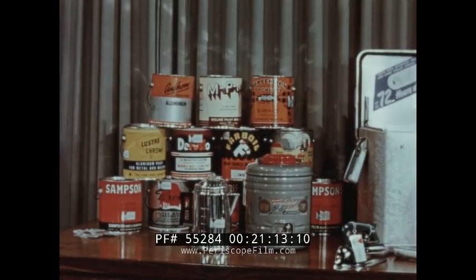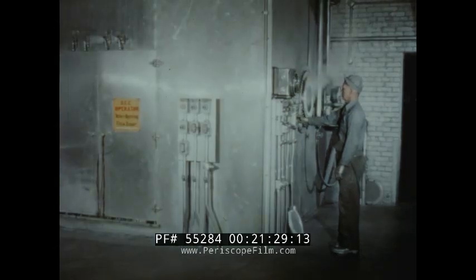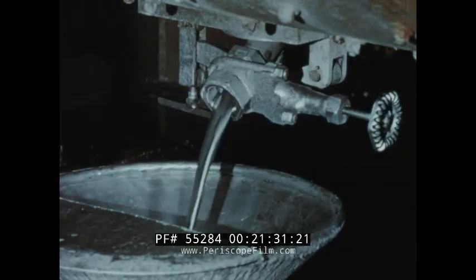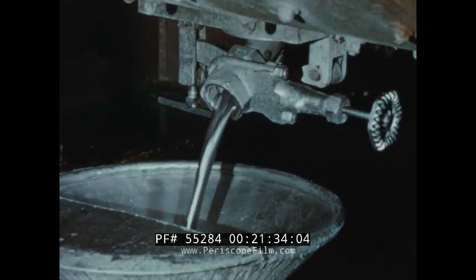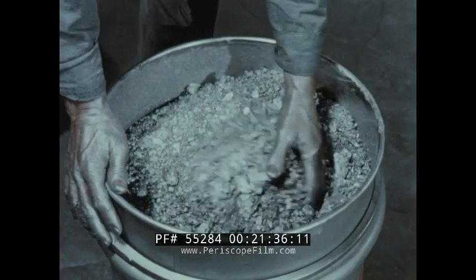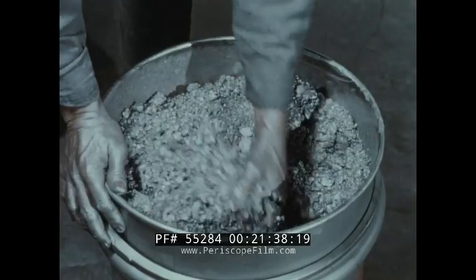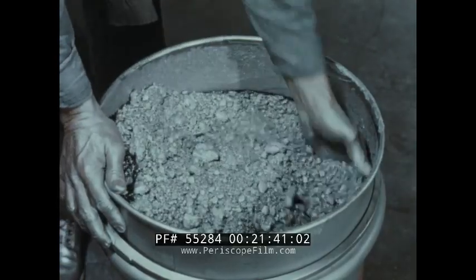Another product produced at Alcoa, Tennessee and Logan's Ferry, Pennsylvania is Albron, which is the name given to the pigments used in the manufacture of paint. To make Albron, aluminum pig is melted and blown through special spray guns to form an atomized aluminum powder. The powder is processed in ball mills to form fine aluminum flakes in a kind of sludge. After filtering, it can be made into powder or paste, both of which are used for pigments for paint.